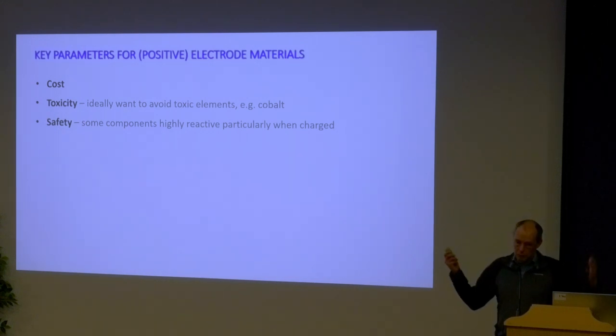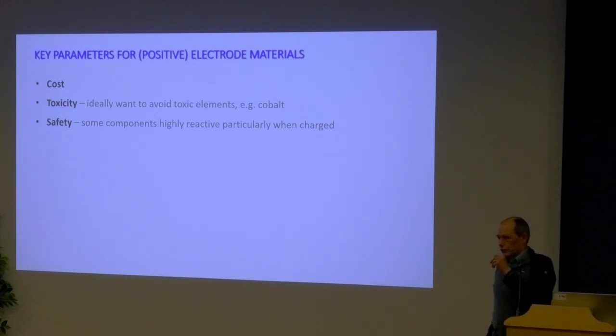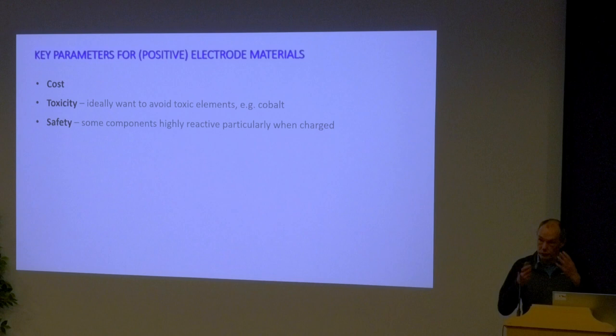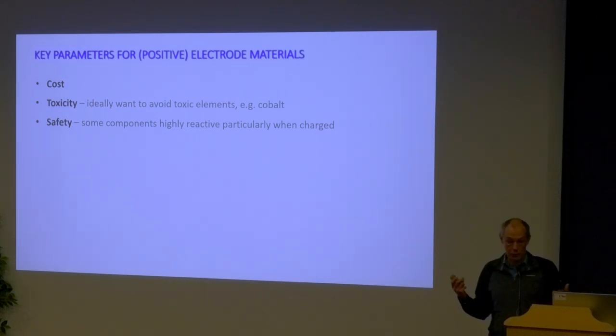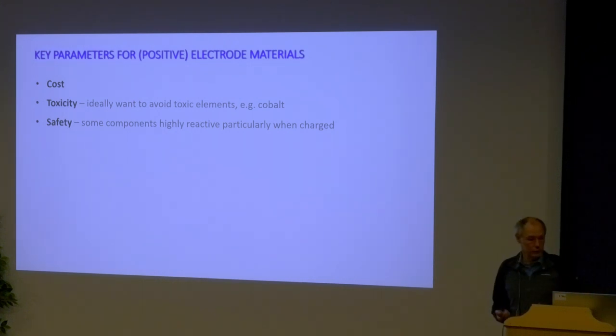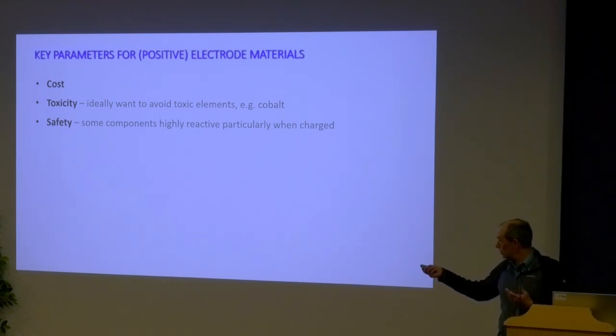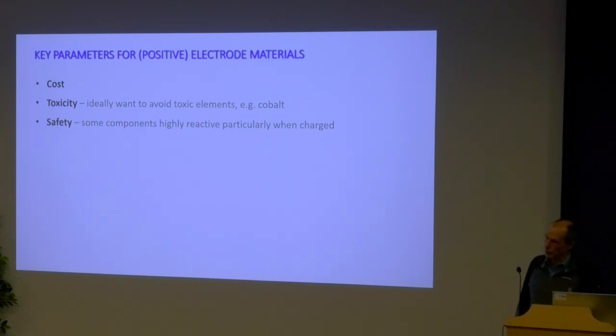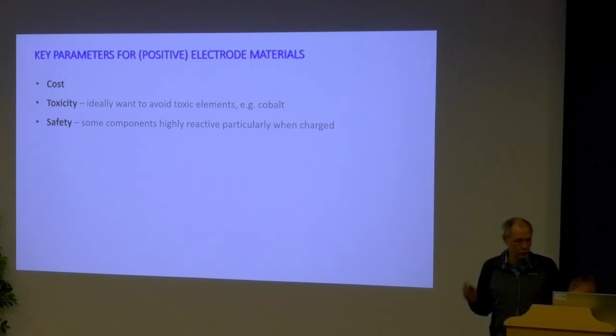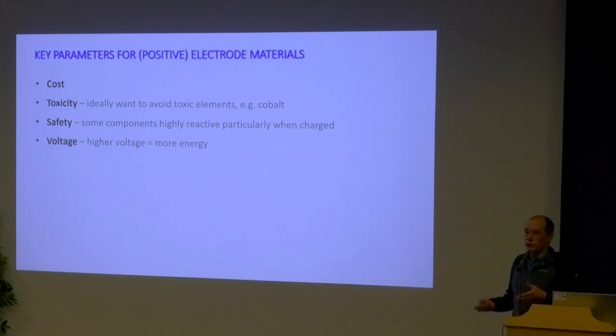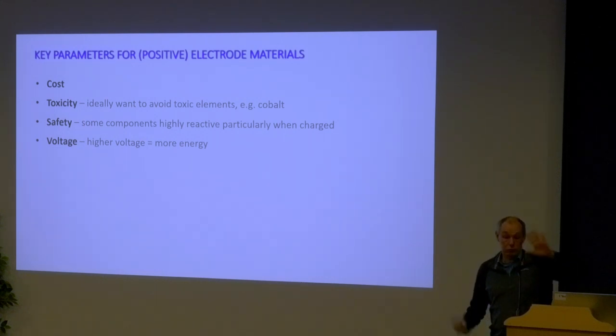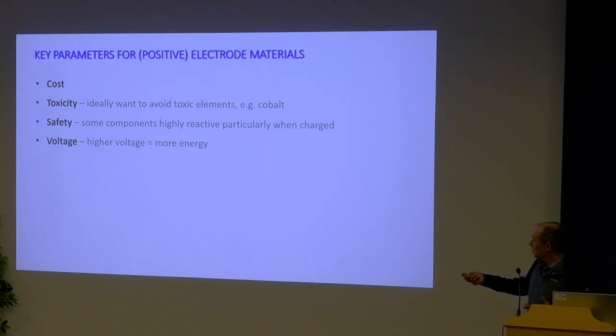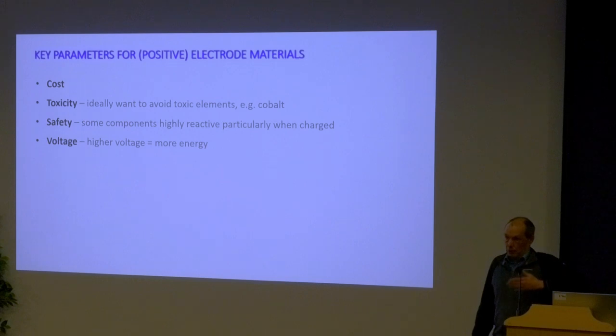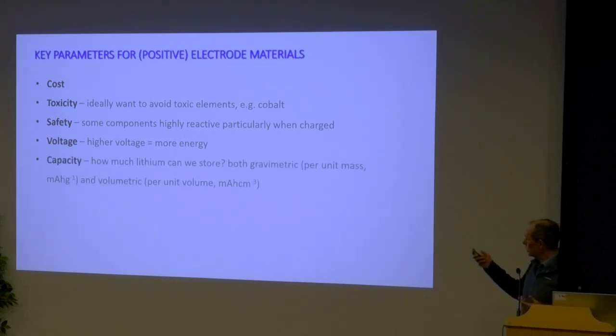Safety. We've got to consider the safety of the battery as a whole, and also when we charge the battery up and so on, we're often creating elements in a state where they're highly reactive and they're not very safe. For example, cobalt, when you charge the battery up, you're forming cobalt 4 plus. Cobalt 4 plus is quite reactive. So, again, issues there. Voltage. The higher the voltage, the more energy we can get out of the battery. So, if we extract lithium from a material at higher voltage, then we can get higher energy. That comes with compromises. Often, the electrolyte material is not stable at high voltages, so we have a series of compromises.